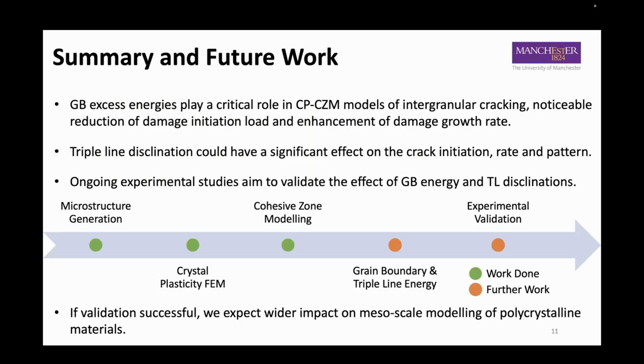So to conclude, our simulation so far has discovered that grain boundary excess energy, triple disorientation, and triple line disclination play a critical role in the crystal plasticity and cohesive model of intergranular cracking. Not only the load needed to initiate the damage, but also the damage initiation point and how the damage propagates. So we are now conducting an ongoing experimental study to validate that hypothesis and to check the effect of the grain boundary energy and the triple line disclination on the material behavior. So if our validation is successful,